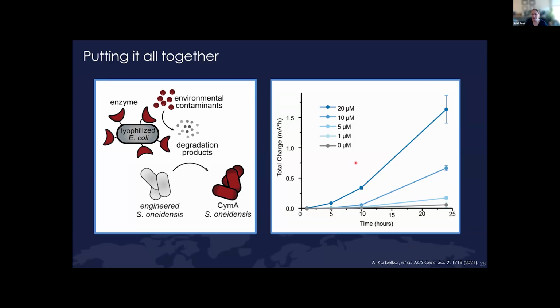What was even more surprising to us, though, was that this is actually quantitative. So as we increase the concentration of pesticide from 1 micromolar to 20 micromolar, we proportionally increase the total charge. And our limit of detection with this is now sub 1 micromolar. And so what that means is we've now lowered our limit of detection by almost 2 orders of magnitude, by almost 100x, by simply moving from absorbance measurements to biological systems. And now we're also below the toxic limit of this compound. So our limit of detection is now well within a relevant range to prevent poor health outcomes.